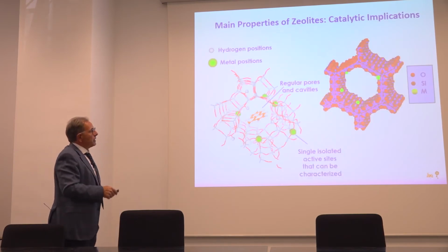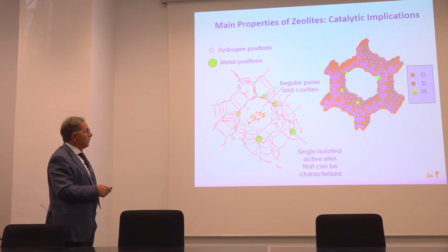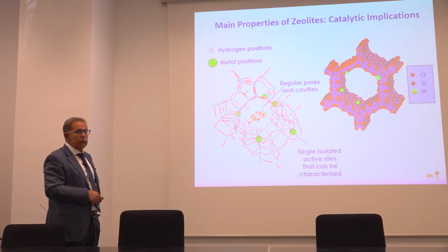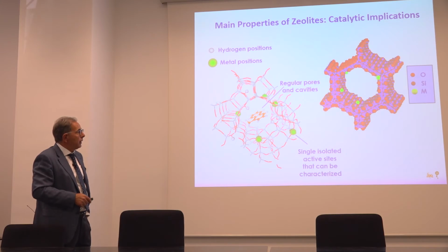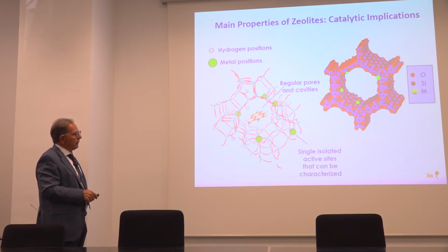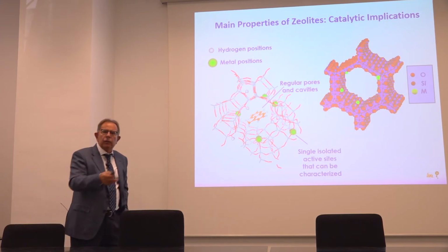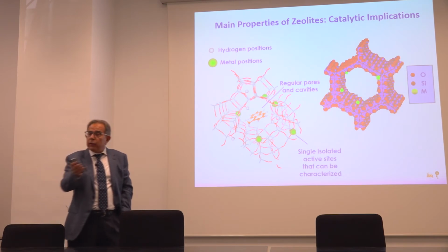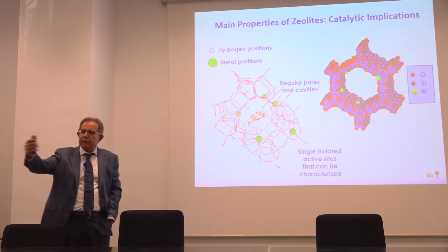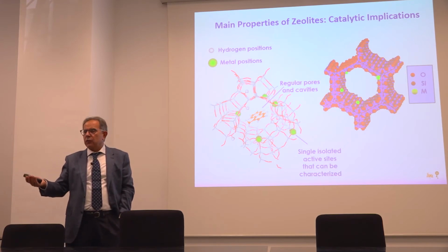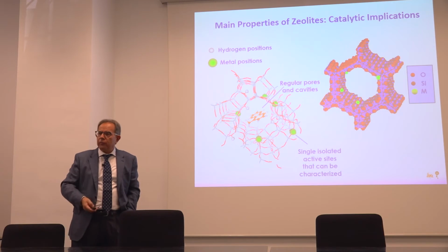And here we have a silicate, more specifically a zeolite, in which we have short range and long range order, and we have a mesoporous material, for instance, with long range order. But let's concentrate on the zeolite here. Here in the framework, we can now do isomorphic substitution. We can substitute silicon with other metals. If we use a trivalent metal, we'll generate acid sites. But we could also substitute with some transition metals. We can substitute with titanium, for instance.